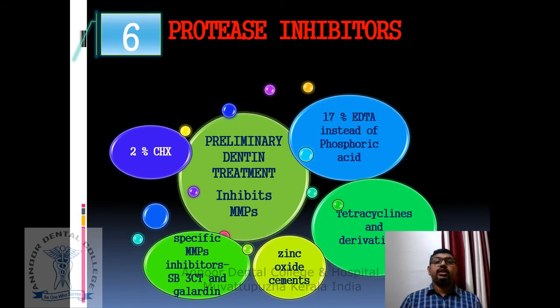So you need protease inhibitors. One very effective protease inhibitor is chlorhexidine in a concentration of 2%. That is why it can be used for rewetting the tooth surface. It inhibits the matrix metalloproteinases, plus it raises the collapsed collagen mesh also.